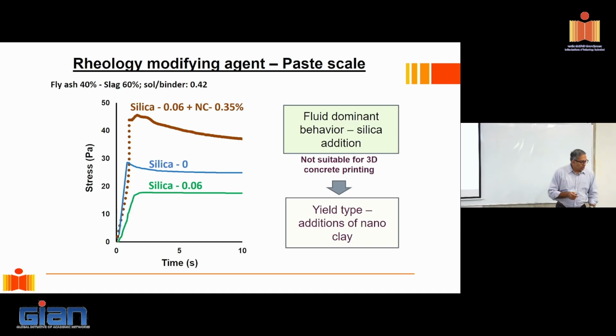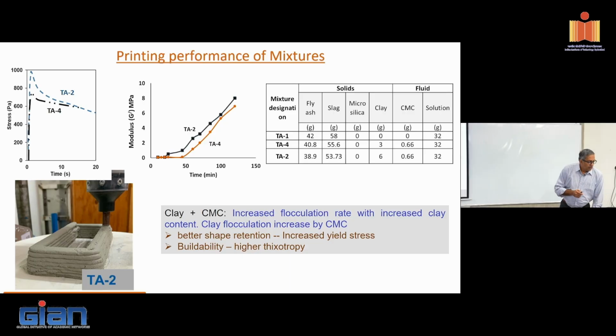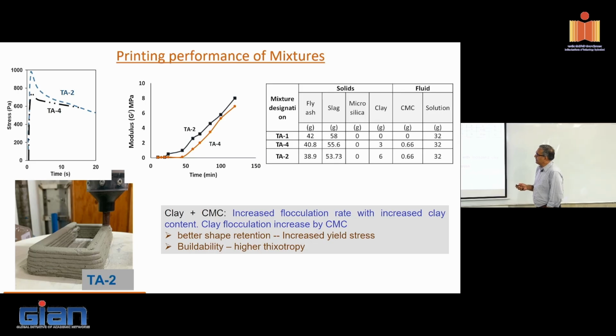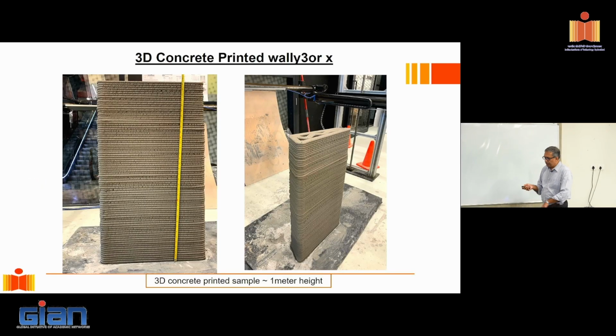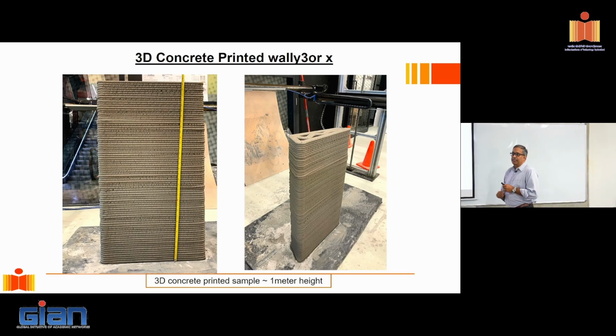And in fact, even the thixotropic measurements, which I'll show you in the next slide here, also start improving. This is also a measure of modulus, which I think Narayanan presented yesterday, which presents the stiffness of the material. Okay, why is stiffness important? It controls the deformation. So what happens when I add clay into this material? Well, my stiffness buildup happens much quicker and it's able to keep its shape. It doesn't deform that much. Okay. Now with that, then we were able to produce 3D printed concrete panels, okay, by controlling the rheology of the alkali activated binder. Okay, if you don't control the rheology, you run into one problem or the other.